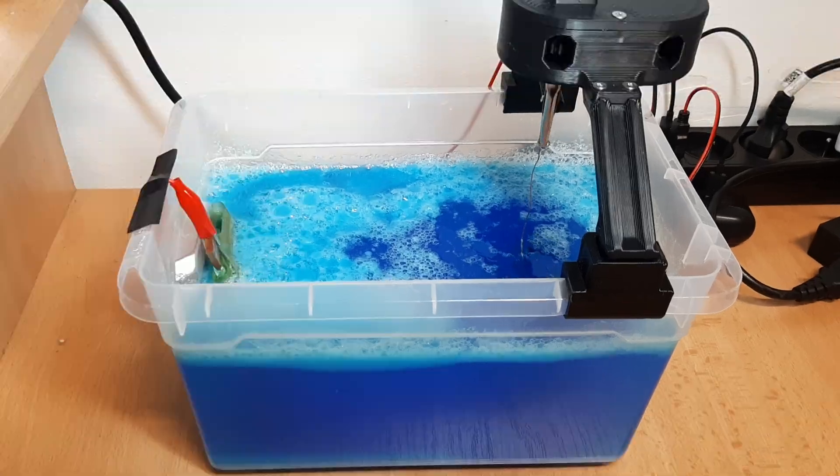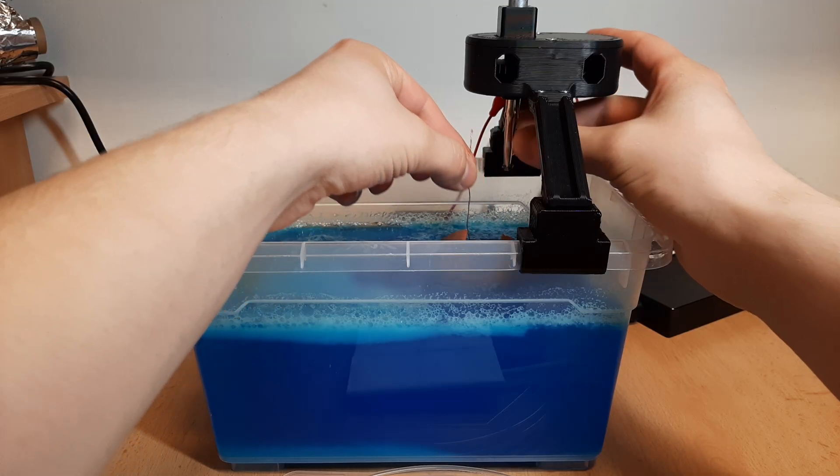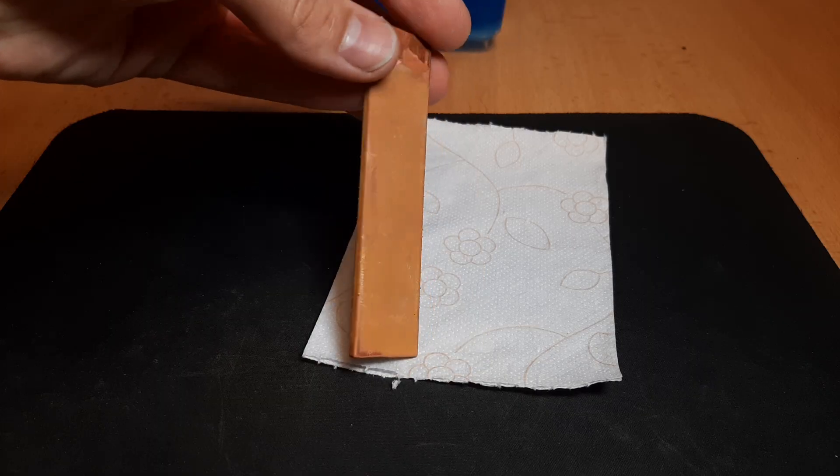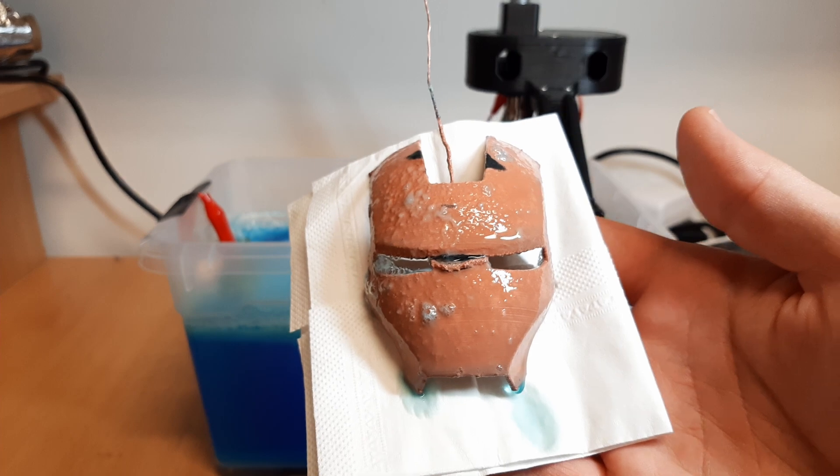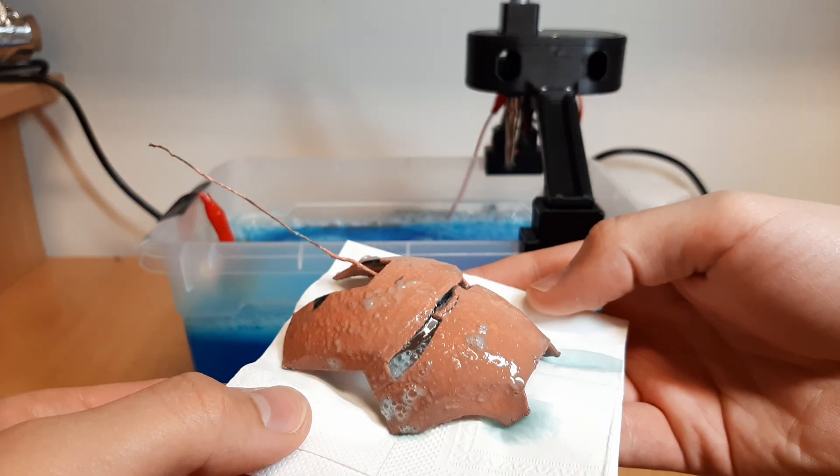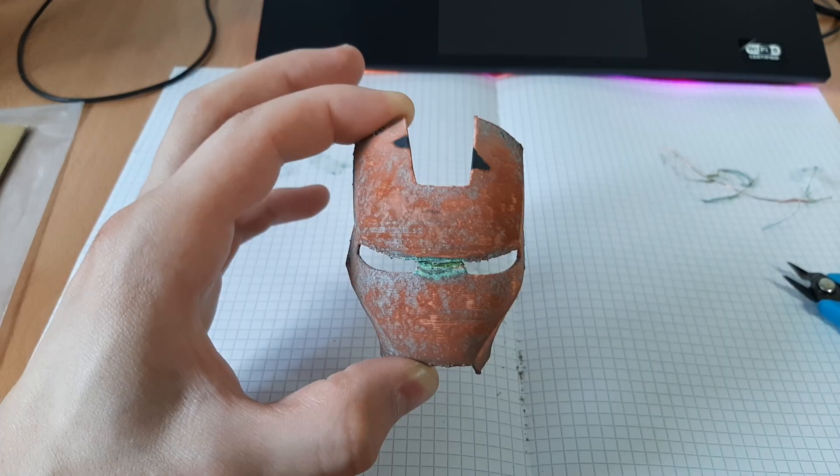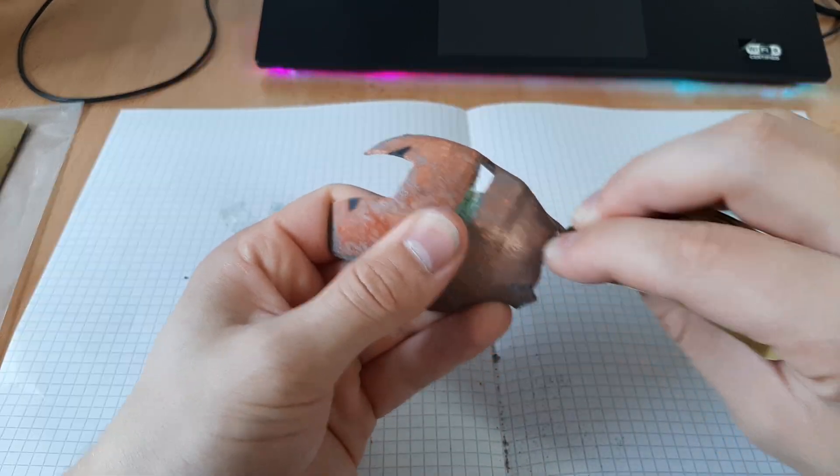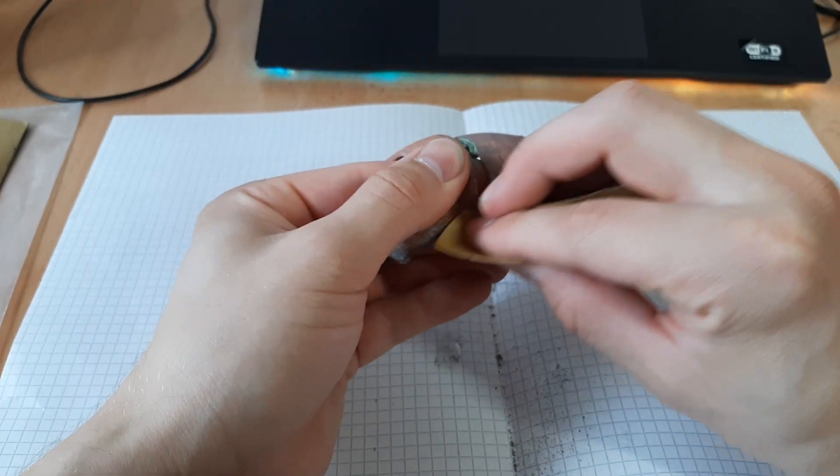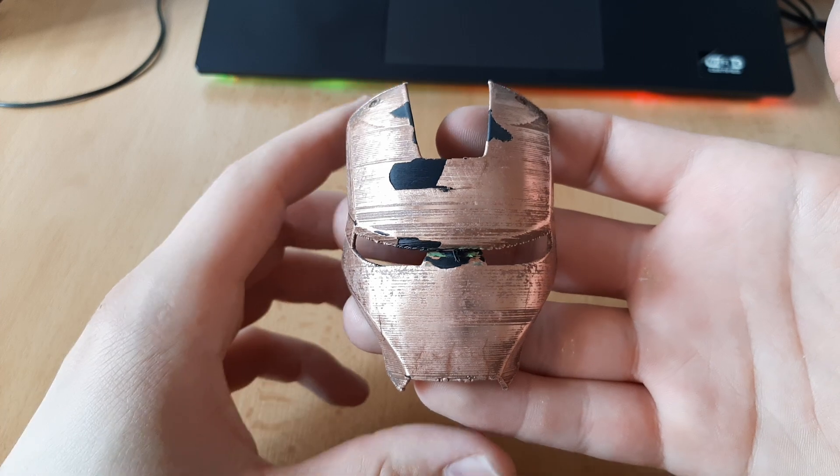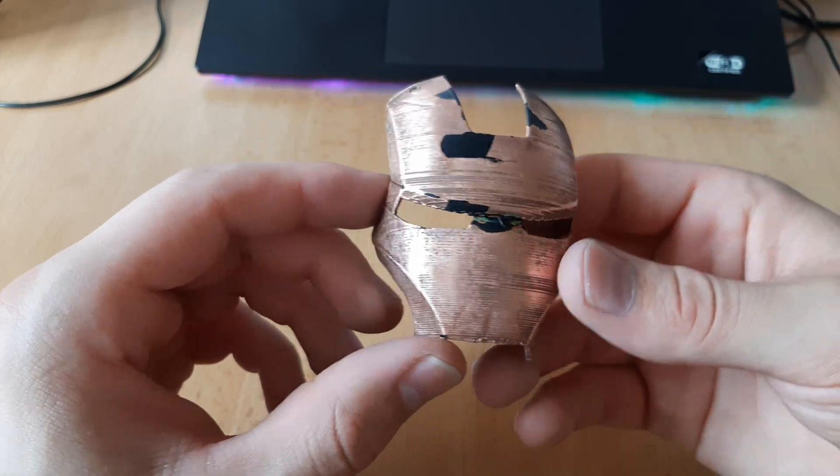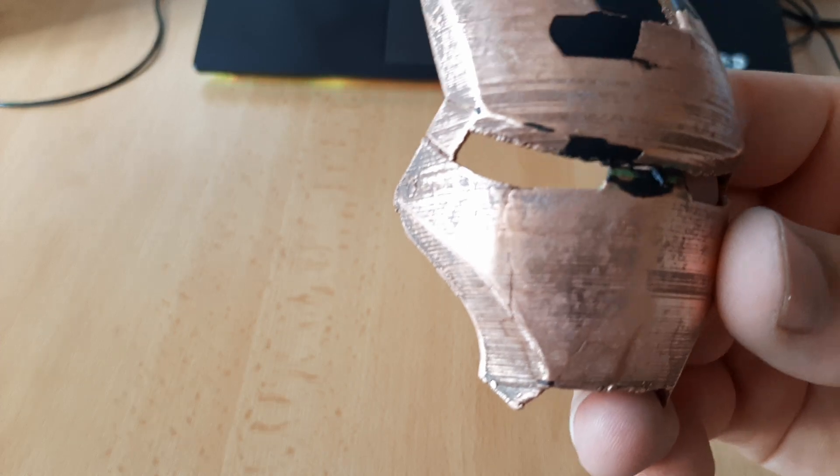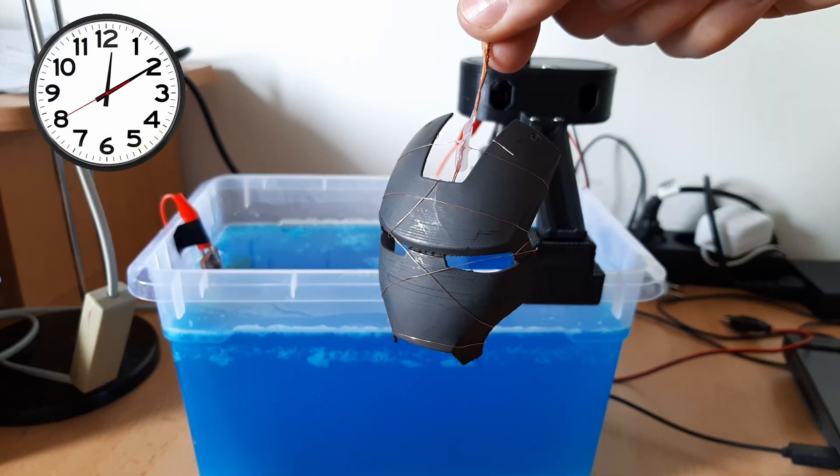Alright, I think the helmet should be plated by now. Let's take it out and do some final touches. The copper anode is a bit corroded. The helmet is covered with the gelatin. I think 20 grams was too much. I removed the wire and then started sanding the copper down. I went from 400 grit all the way to 1500. Some of the copper peeled off and it doesn't look the best. The copper layer is too thin. You can also see the lines from 3D printing.